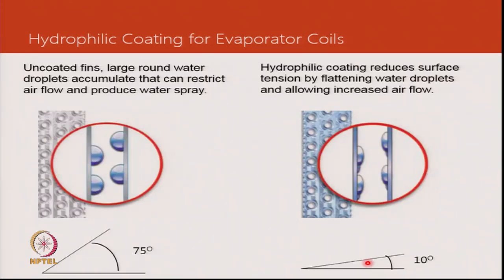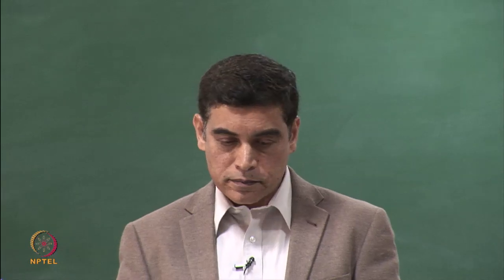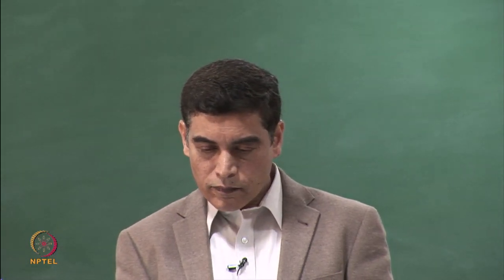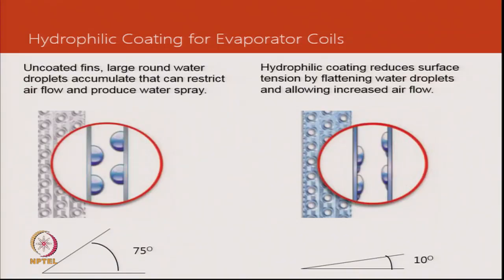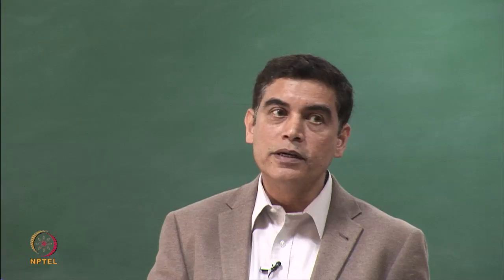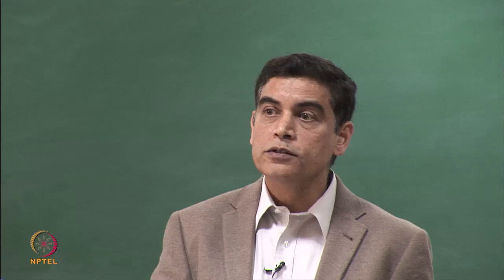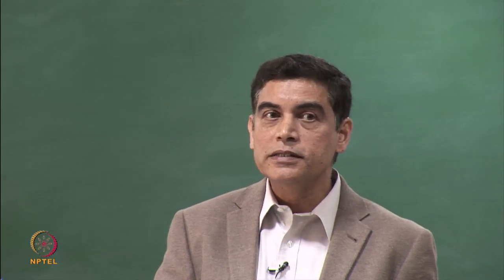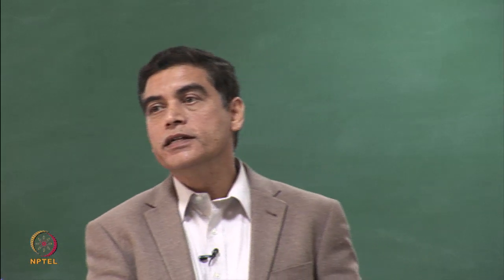So here is the angle of contact. Because the surface tension changes, the angle of contact changes from 75 degrees to 10 degrees, and this leads to better flow of condensate into the drain pan. This becomes handy when there is a lot of high air velocity in certain parts of the evaporator. The droplets being thrown in a tangential blower because of the velocity being high in certain part of the coil, it addresses very well. So, split systems you will normally see have a blue coil, and that is an indication that a hydrophilic coil has been used there.